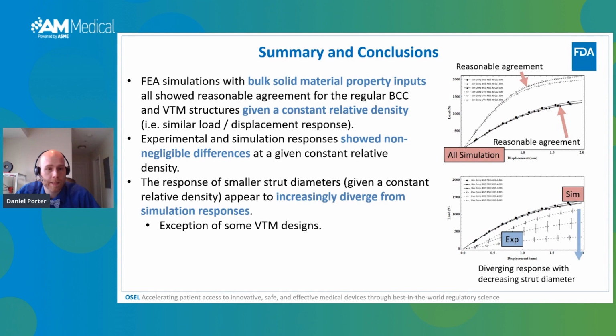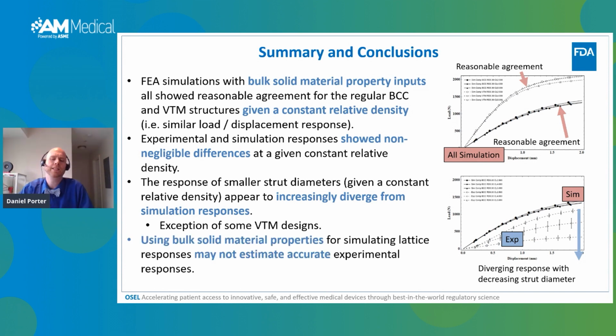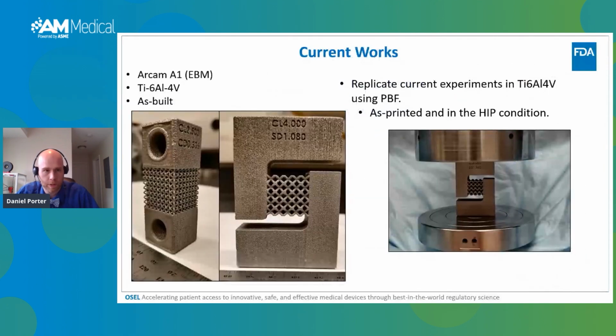And as the strut diameter decreased, we had an increasing divergence from the simulation response. And that's shown in the graph in the bottom right here. So simulation lines up, and then as the experimental struts get smaller, they start to fall off. And so we end with the point that using bulk solid material properties for simulating lattice responses may not necessarily give you accurate estimates of experimental responses. Other considerations may need to be implemented if you want an accurate simulation. You probably need some decent validation activities involved. So I'll quickly go into current works.